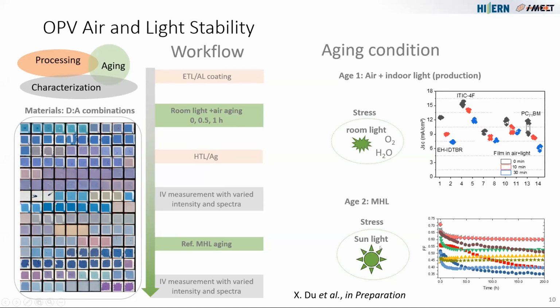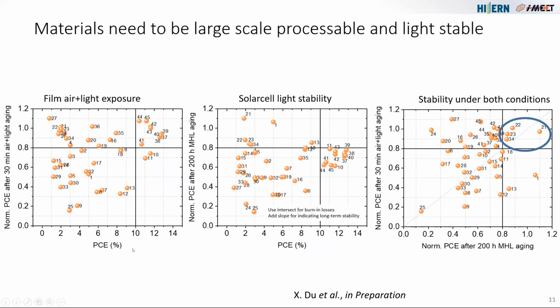And so now for all of these combinations, we know how sensitive they are to air and how sensitive they are to light when air is excluded all the time, which allows us to make these plots where we can basically plot the efficiency of a combination over its air stability, or the efficiency over its light stability after 200 hours. Or here in the last plot, we were plotting the light stability over the air stability. So basically, we can see which cells lost very little performance under light degradation, which is all of these cells here. And then we can also look which cells are in addition stable to processing in air. And we can basically hone down the most promising materials combinations from all the systems we've been testing.